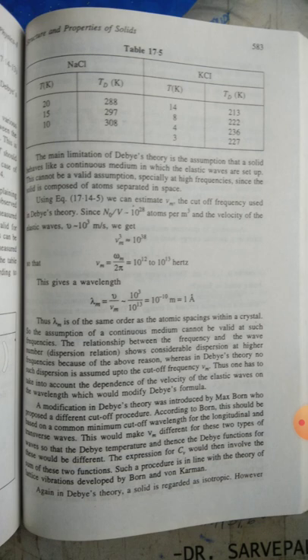The main limitation of Debye's theory is the assumption that a solid behaves like a continuous medium in which elastic waves are set up. That cannot be a valid assumption, especially at high frequencies, since the solid is composed of atoms separated in space. We can estimate νm, the cutoff frequency used in Debye's theory, since N0 by V is 10 to the power 28 atoms per meter cubed, and the velocity of the elastic wave v is approximately 10 cubed meter per second. We get νm cubed approximately 10 to the power 38, and νm is equal to ωm by 2π, equal to 10 to the power 12 to 10 to the power 13